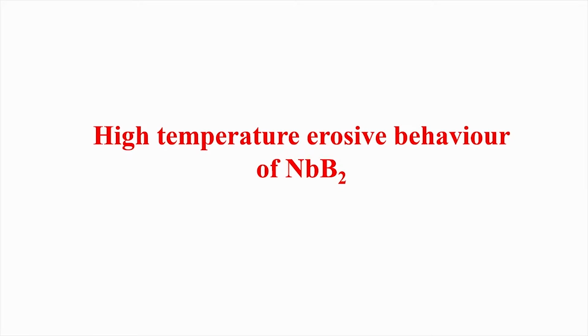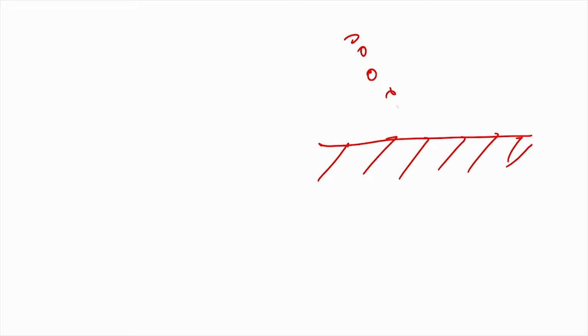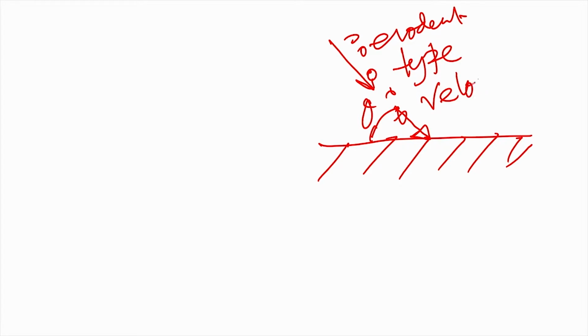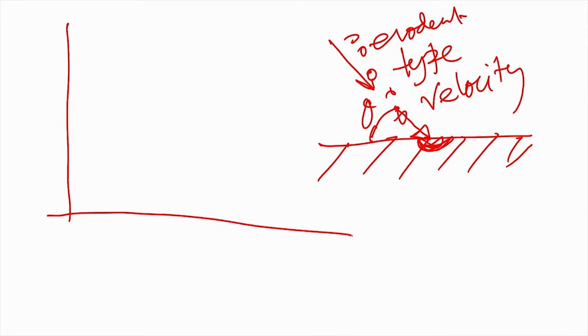Now, before I explain that high temperature erosion behavior, erosion essentially means that you have a flat surface, right, and you have erodent particles. These erodent particles will be impinging at an angle theta, and they strike the material as a stream of erodents at a particular speed. Depending on the erodent type and velocity, this flat material would experience wear and form a crater with subsurface deformation. This particular erosion wear loss, in the case of metals, you can find out by measuring the changes in the weight.